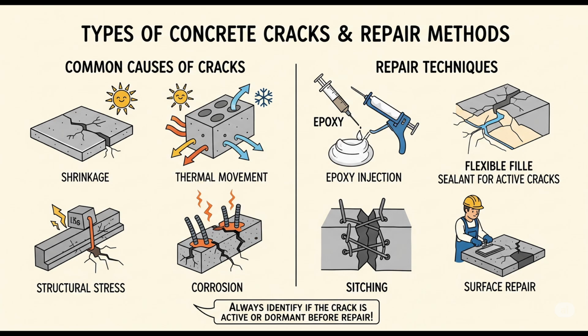And what causes those inclined shear cracks specifically? They're often caused by things like low concrete shear strength or maybe inadequate shear reinforcement, meaning the stirrups, those small loop-like pieces of rebar that wrap around the main bars, are spaced too far apart or there aren't enough of them. Poor detailing, like improper welding of the main longitudinal rebar and the transverse stirrups, can also contribute. Our source notes that cracks wider than, say, 0.5 millimeters in beams usually indicate significant issues, like overloading or perhaps insufficient main longitudinal rebar to handle the bending forces. It's a clear red flag needing investigation.